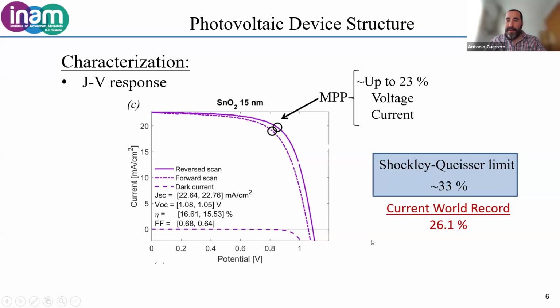The current world record using this type of materials, the perovskite, is in the range of 26% using small area devices. And the limit for single semiconductor solar cells is around 33%. Just to show you here as a comparison where we are, in perovskite materials we are very close to crystalline silicon at the moment. And if issues related to degradation of the materials are overcome in the next few years, most people believe that the perovskite materials will be the next technology to be in the market.